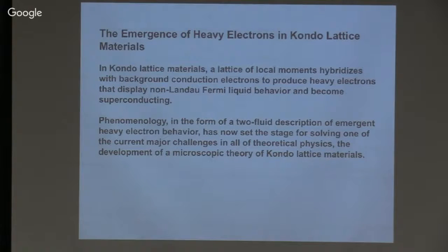And these are the experiments, again from the Taillefer group, that show that this is not restricted to the cuprates. It's true for heavy electrons. It's true for essentially organics. It's true for all of the unconventional superconductors so far. So you're looking at a common mechanism and a common pairing state. You may get a different pairing state from d-x-squared-minus-y-squared, depending on the background band structure, but the mechanism is the same.